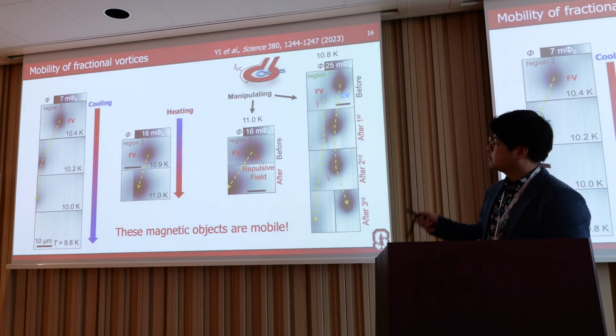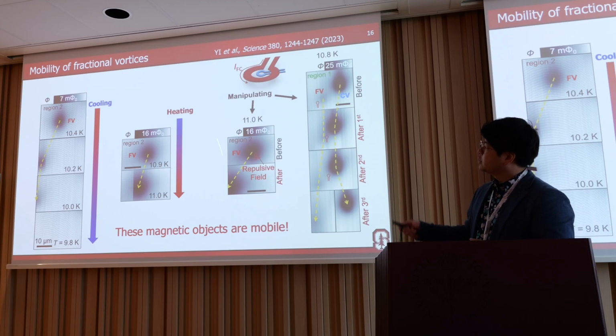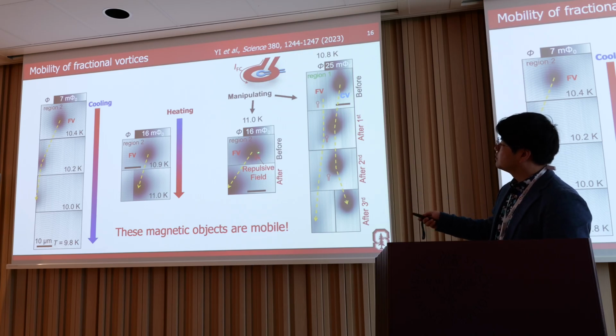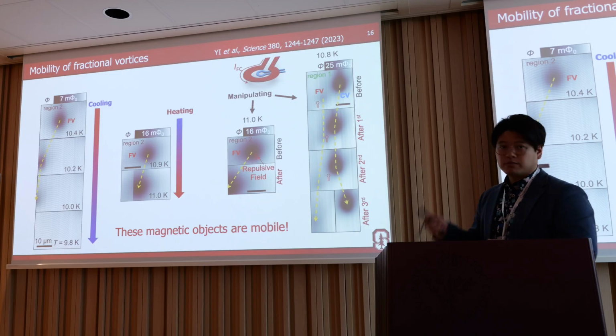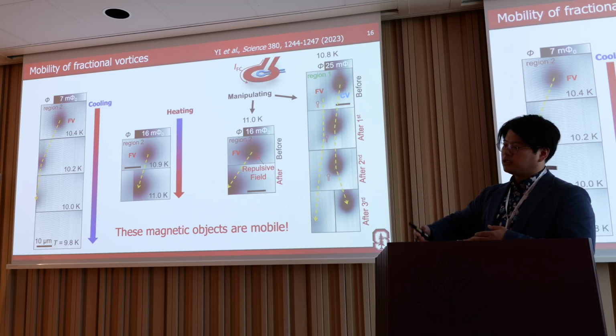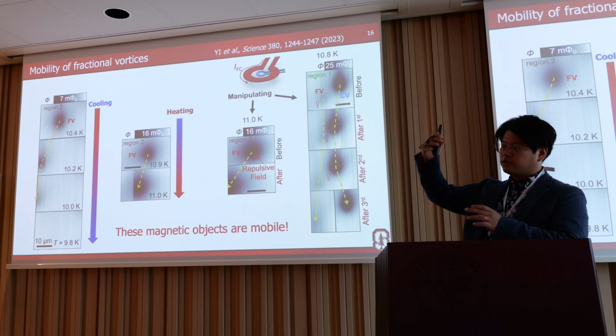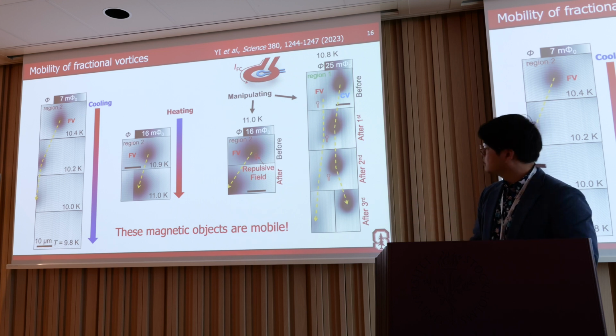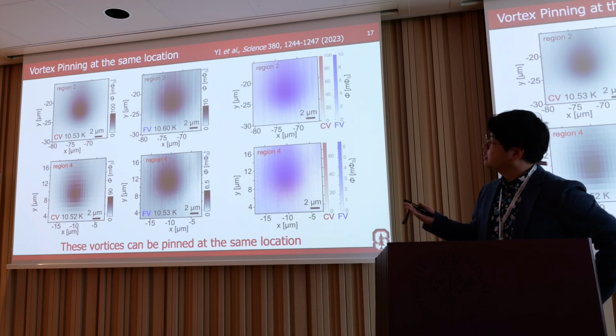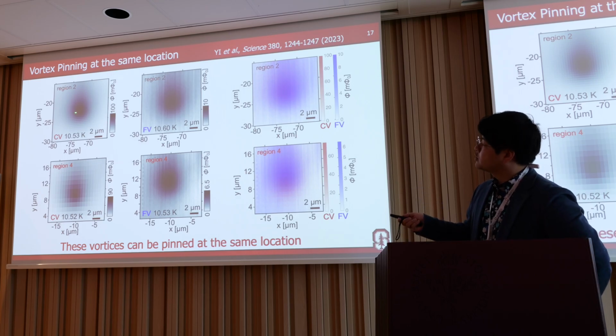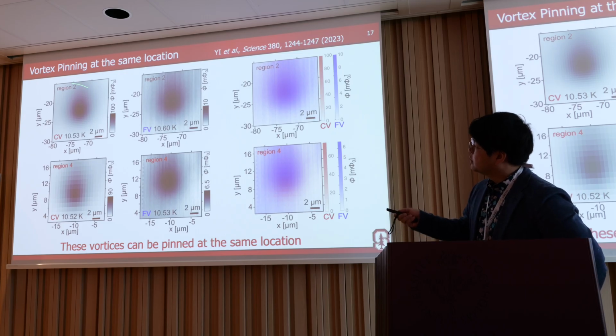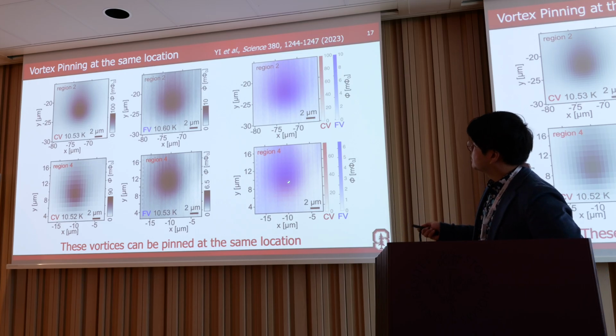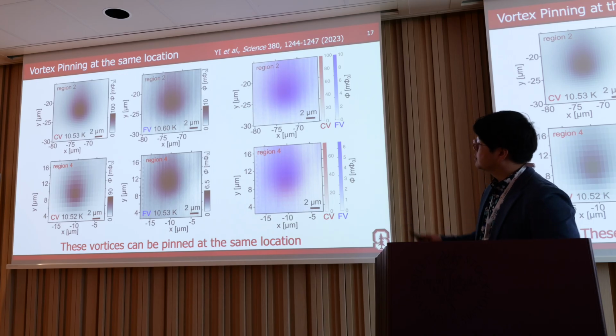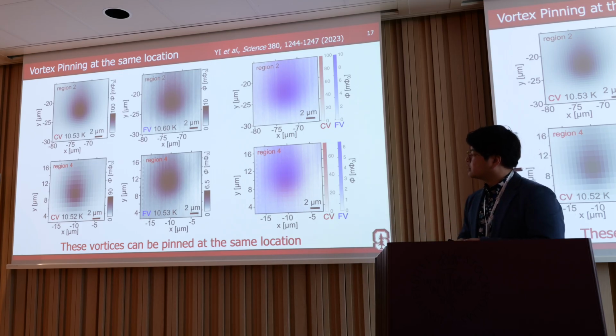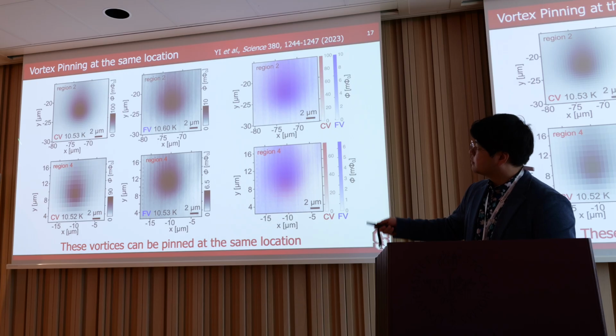For mobility, yes, it's very obvious. It's mobile. While cooling or heating, it hops to another pinning site. And when I apply a magnetic field, it's easy to manipulate its location. So it's obviously a mobile object. So this is a vortex, not pinned at a very special location like a tricrystal junction or some specific magnetic impurities. Because we can manipulate the location, we tried to manipulate the locations under exactly the same conditions for the integer one and the small fractional one. And we successfully can manipulate it, so this small vortex doesn't need special locations, and it's the same as a conventional vortex.